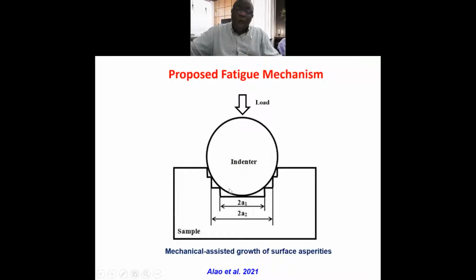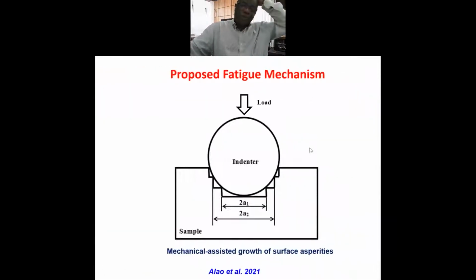So at single load, it will have a deformed surface. When the load increases, there will be deformation along the edge, because that will serve as the stress concentration site. This will further be exacerbated by the surface roughness. So the rougher the surface, the heavier will be the induced damage. So mechanical assisted growth of surface asperities is the proposed fatigue mechanism for the dental restoration that we propose.